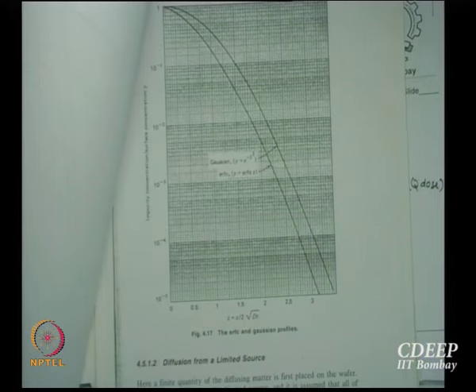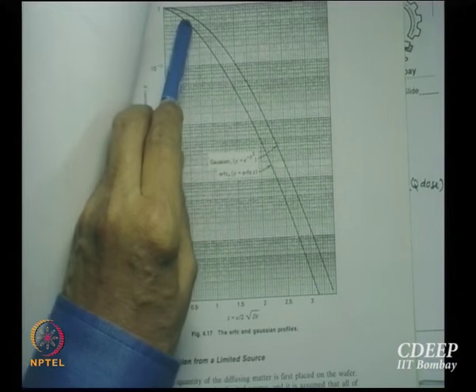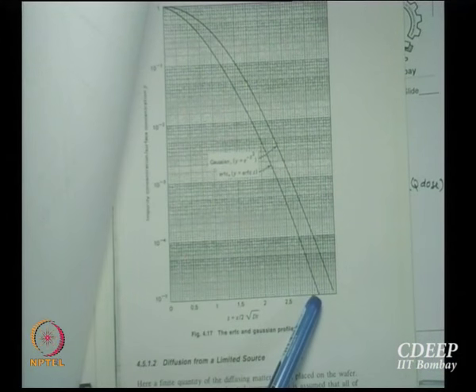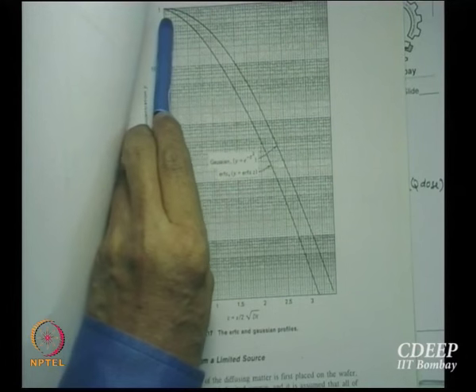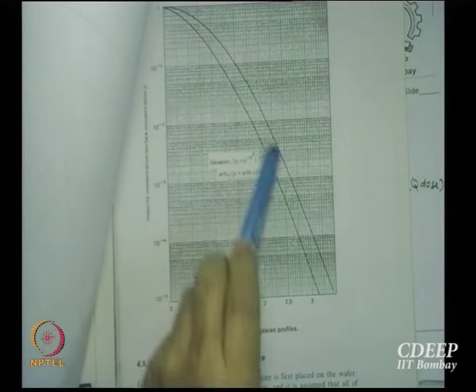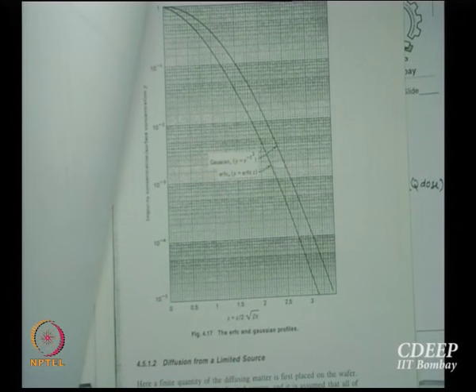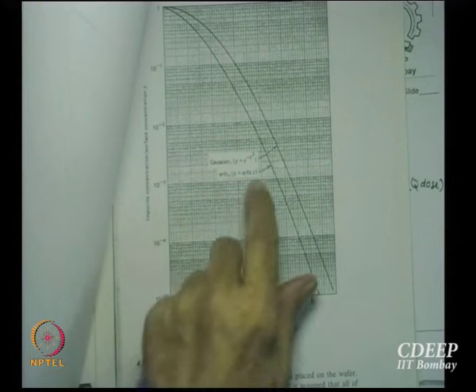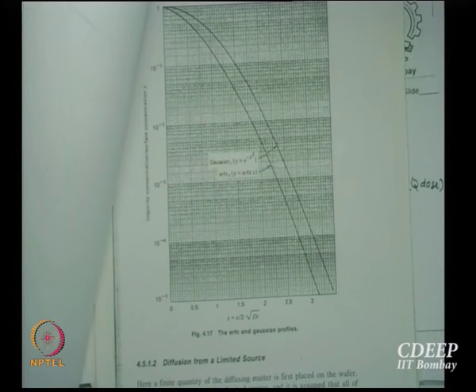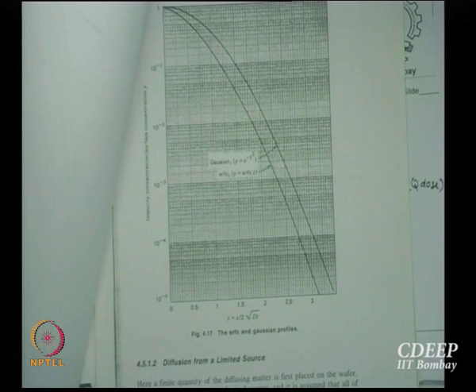Now these are the two profiles, Gaussian and error function. The lower one is the complementary error function and the upper one, assuming the same surface concentrations right now, is the Gaussian profile. The error function and complementary error function profiles look similar but slightly different, because the complementary error function never changes its shape. It may keep increasing at different time and temperature, but the profile will remain. In the case of Gaussian, it starts flattening.